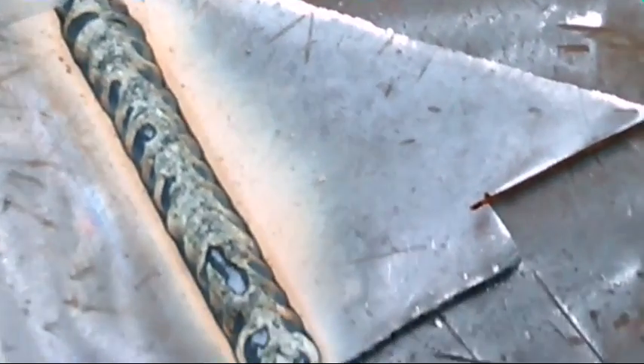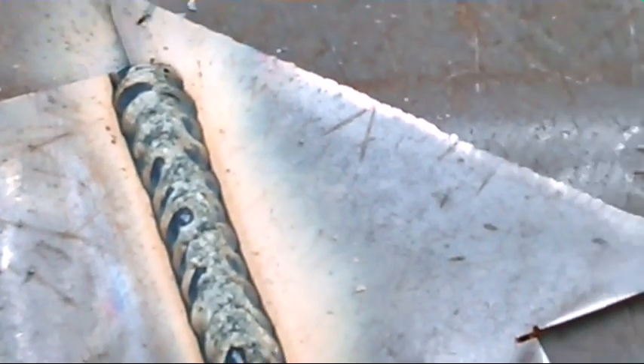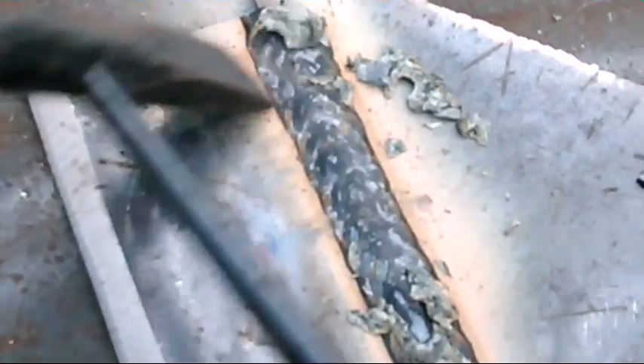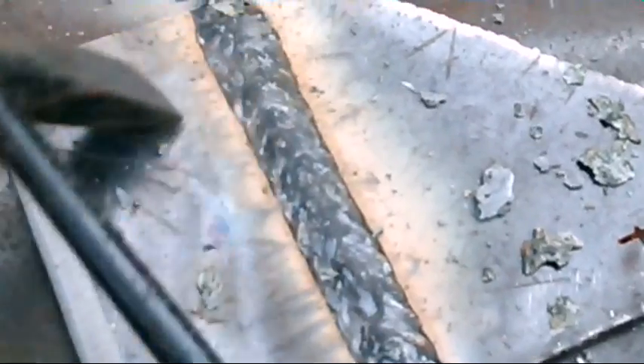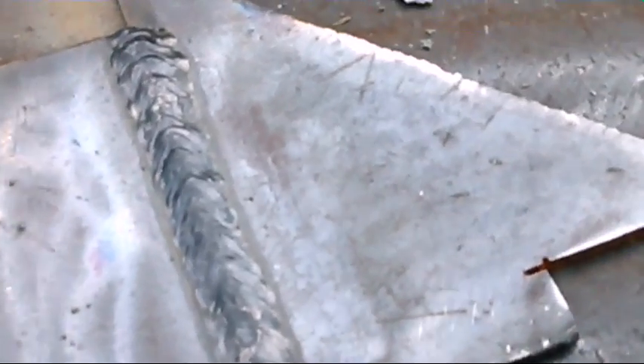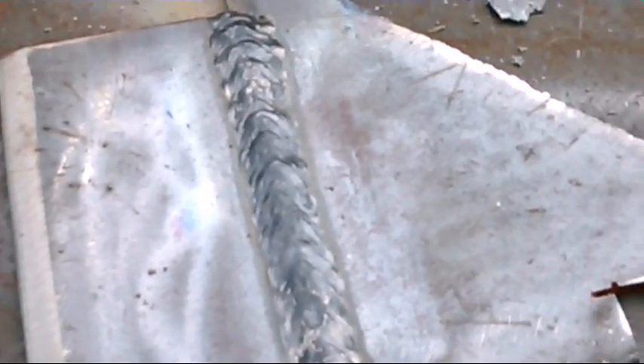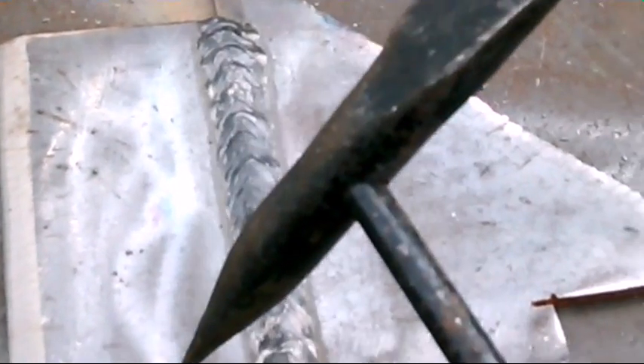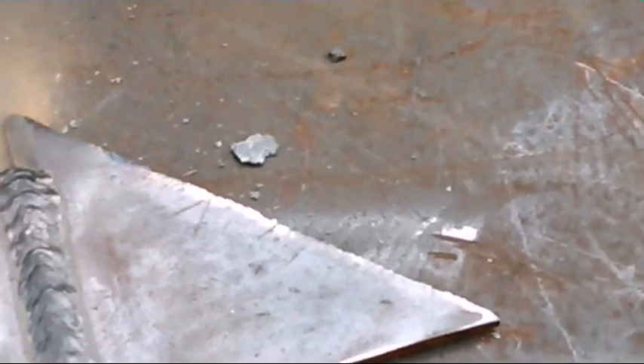All right, on that, I just kind of went side to side as sort of a weave fashion on it. That's the slag on top of it. Usually, it's not too bad for coming off if everything went pretty good, you know. And that's not too bad for it. This is a different process. So it's not going to look like solid wire if that's what you're going for. You're not going to get that. And if you don't have it switched over to DC negative, you're going to end up with so much spatter around here that it's just going to be crazy. It's still got a few pieces there. But if you don't swap over, you're going to end up with spatter everywhere right there. So I'll set up another weld right quick and we'll look at that one.